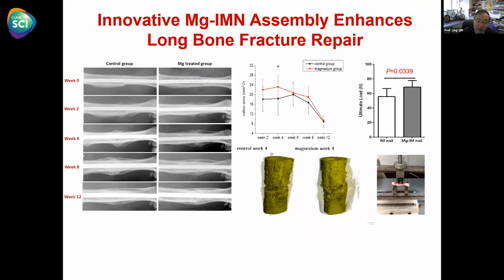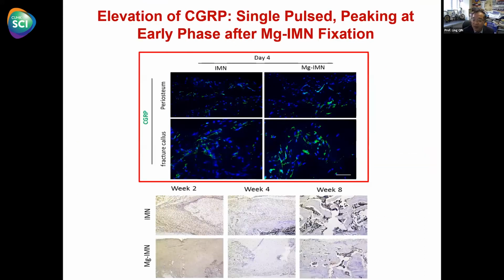Indeed, in the magnesium group, we see a lot of callus formation, particularly in the early phase, which is important for the fracture region without affecting the later bone remodeling to get back to normal. Mechanically, there is around 30% improvement.